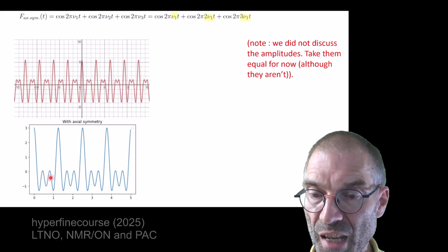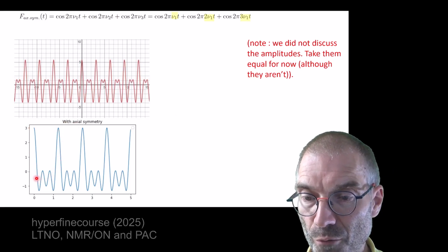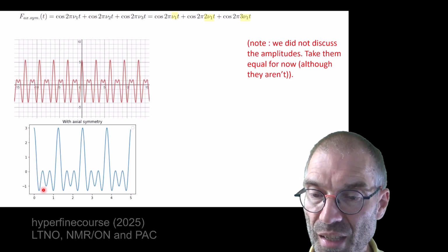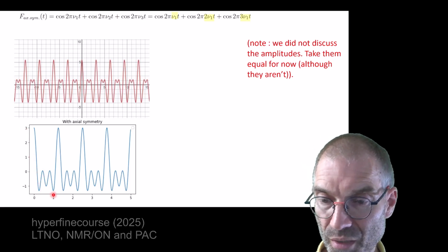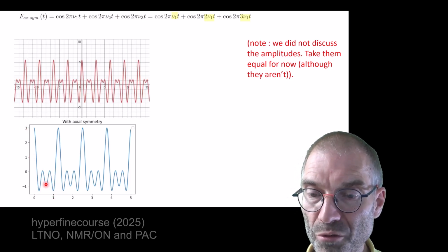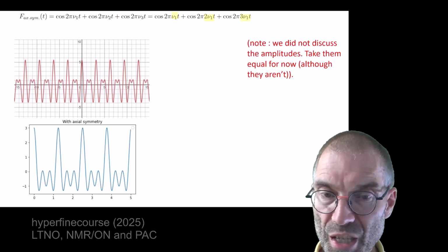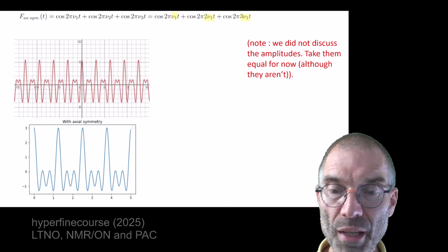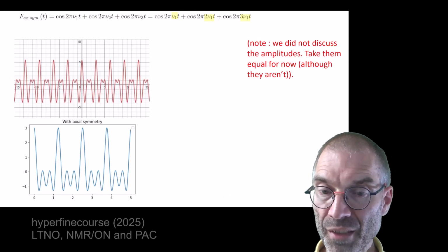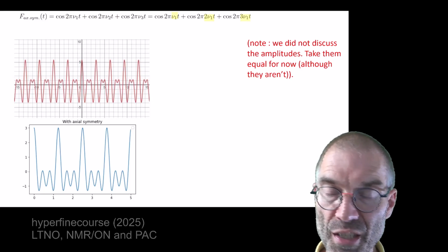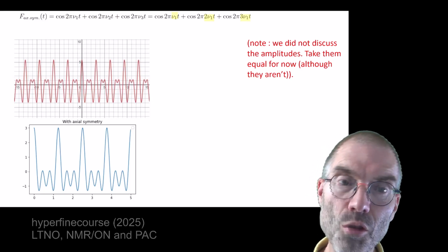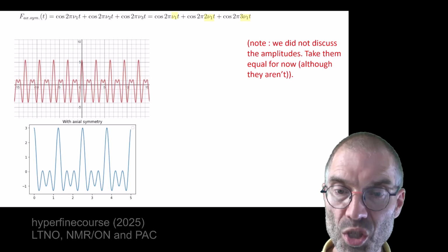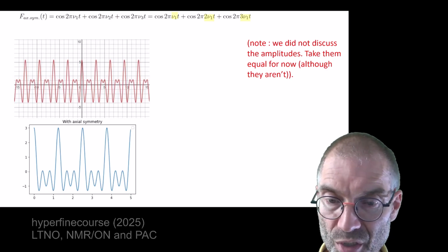An oscillation with the first frequency, and then this typical structure on top of it. If you see this, that will always be in PAC a reflex: aha, this is an axially symmetric field gradient for spin 5 half, which is for PAC the most often situation.